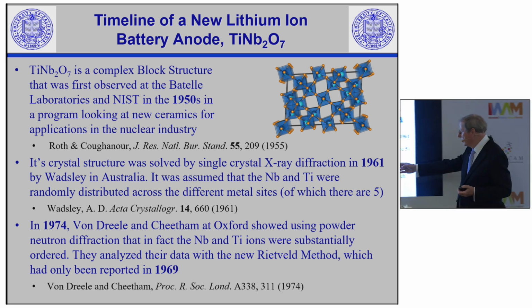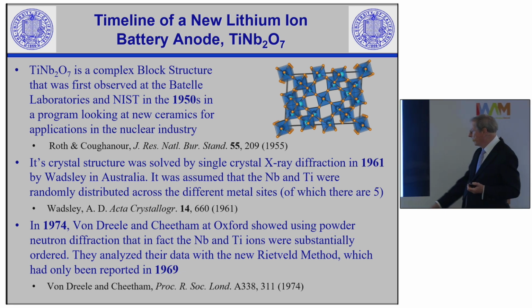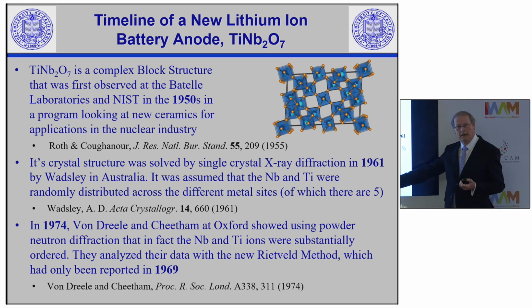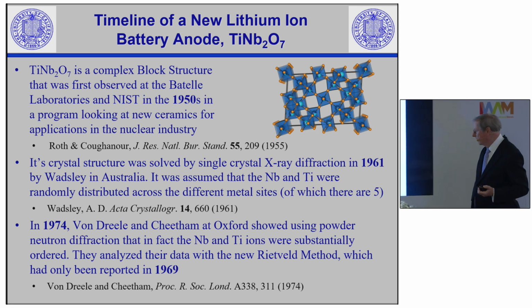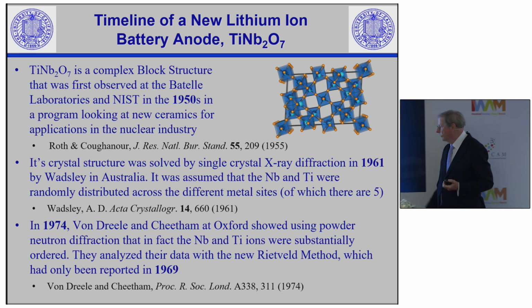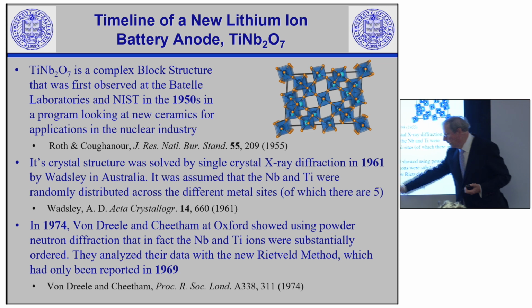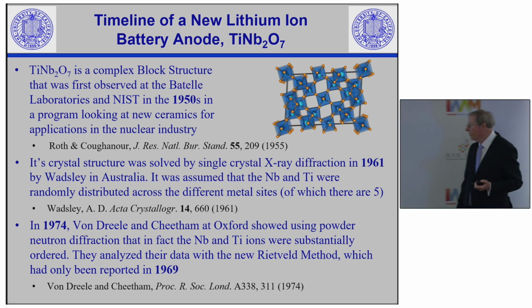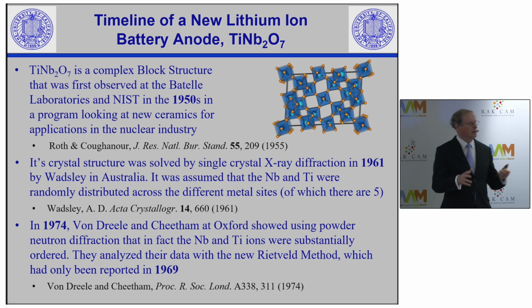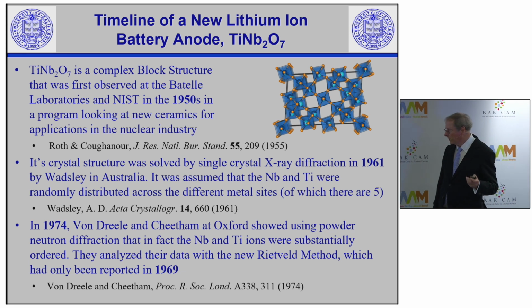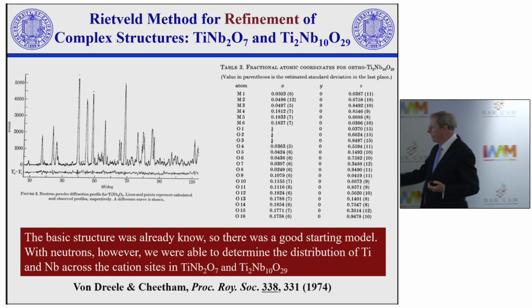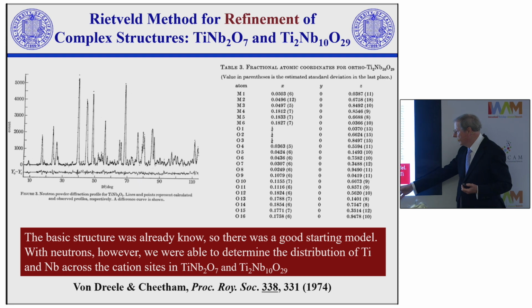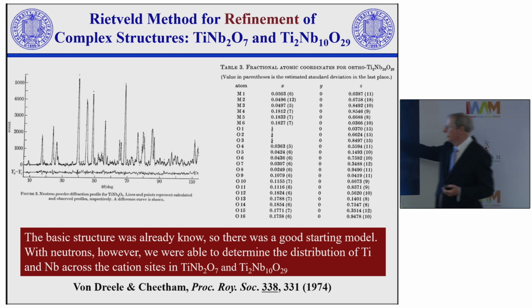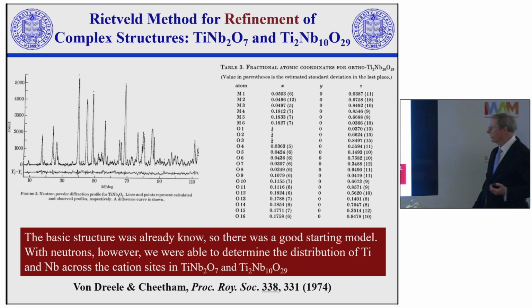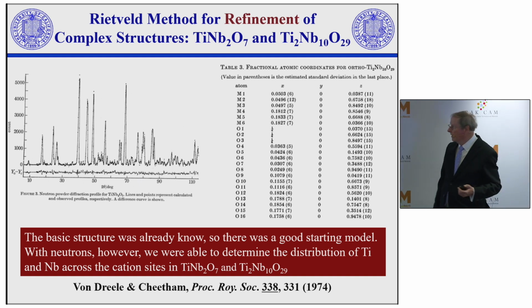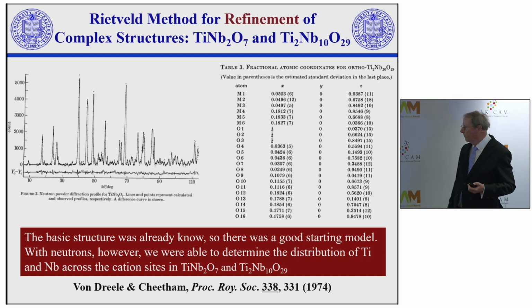And so we used a very new method at the time, which is called the Rietveld method, which some of the people in the audience will know about, which was only launched in 1969 for refining complex structures with powder data. So this is our paper in 1974, determining the structures of the titanium niobium oxides, TiNb2O7, and another more complex one.